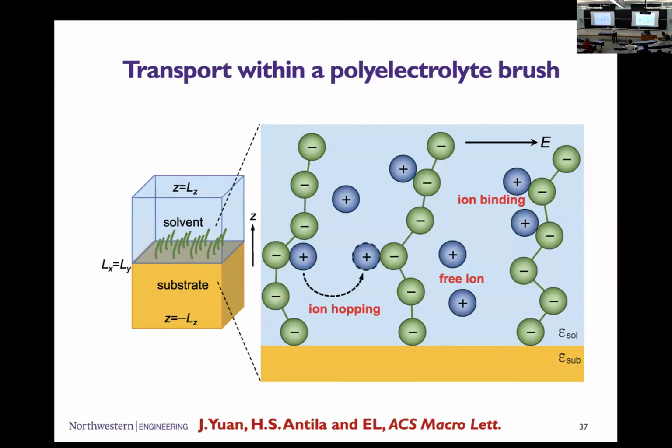We showed that you can actually control the ionic flow not only by the rate, let's say the density, at which the polymers cover the substrate, but also by the dielectric constant. So we found this whole world of dielectrics, lots of surprising phenomena. And this is a simple simulation again, because it's a flat surface, you can just use image charges. This simulation is barely slower than a standard simulation. And I really think that's important to bring up in a workshop like this. You can make advances that haven't been done before, and find lots of interesting things at an expense that is really modest.